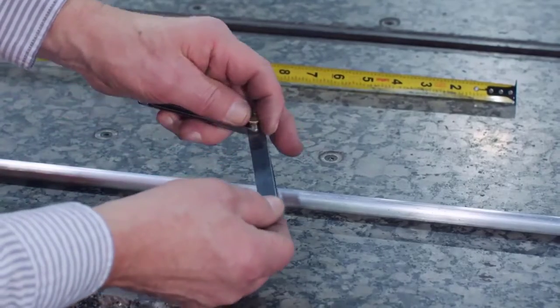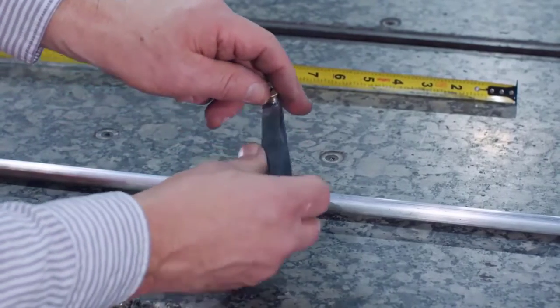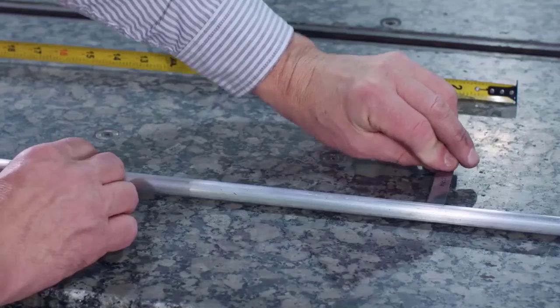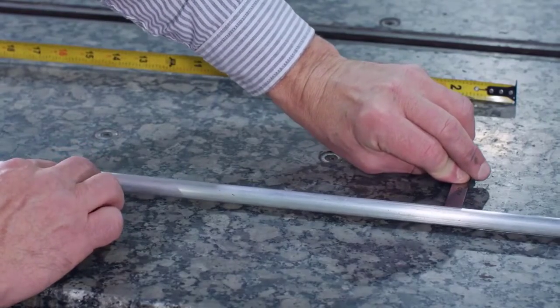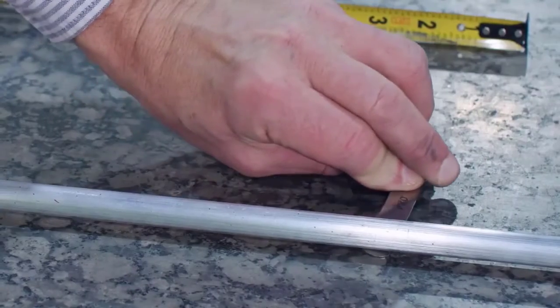Now to actually measure the rod, we will need a feeler gauge. We'll take the feeler gauge and insert it into the gap and find it measures twenty-four thousandths of an inch.